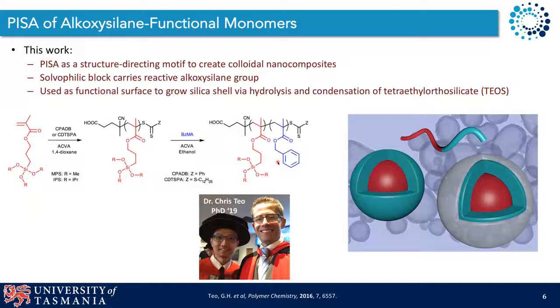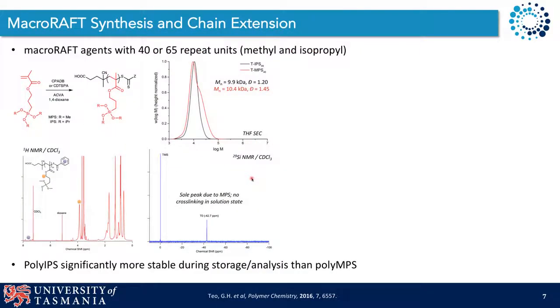All things going well, this alkoxysilane group is still active after the second step and can be used to grow a silica shell via subsequent hydrolysis and condensation of a tetraethoxysilane precursor such as TEOS, preserving either the spherical or vesicle or capsule-like morphology formed during the polymerization. So Chris, who recently graduated, started off by making a variety of macro RAFT agents using both the methyl and isopropyl versions of this alkoxysilane, targeting 40 or 65 repeat units respectively, with reasonable control of the molecular weight distribution. There are some slight variations between the methyl and the isopropyl version.